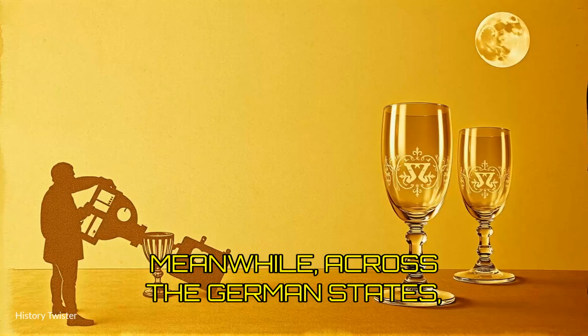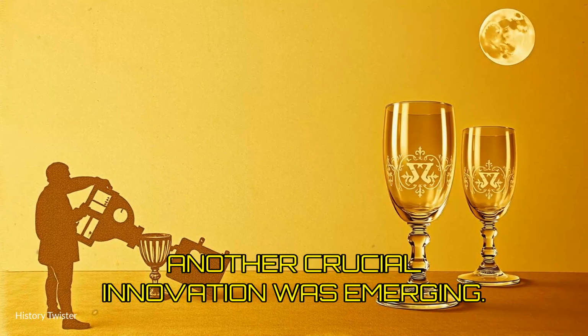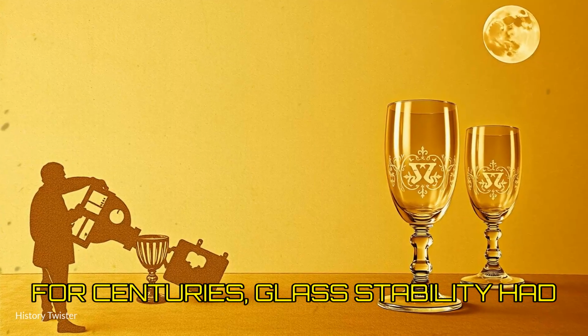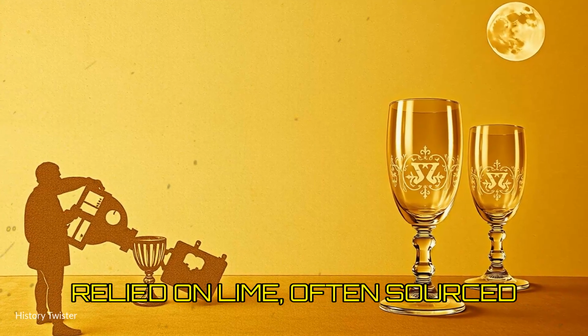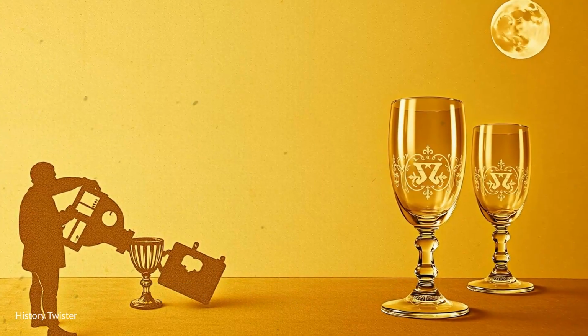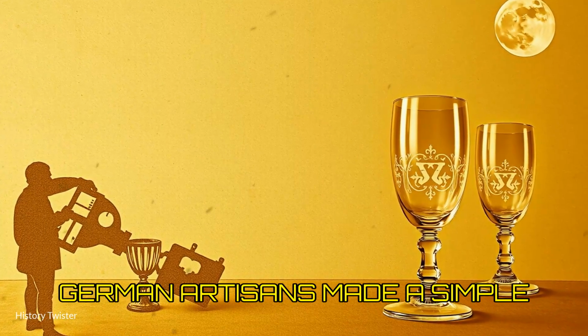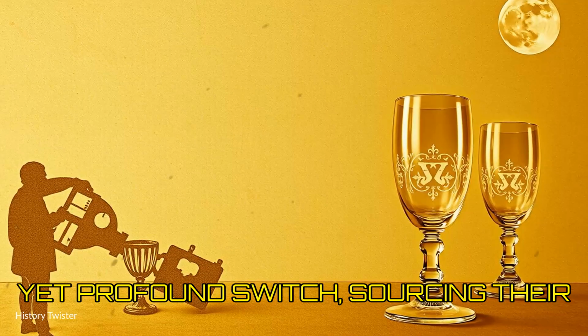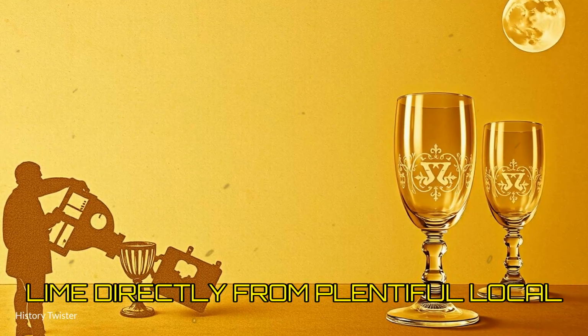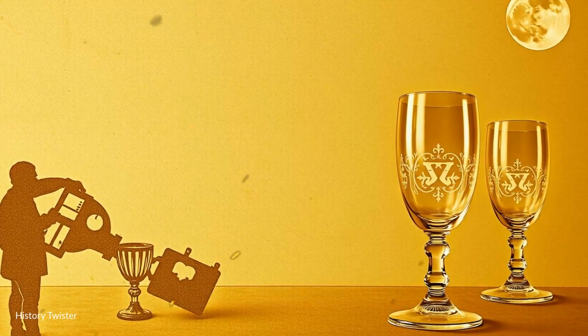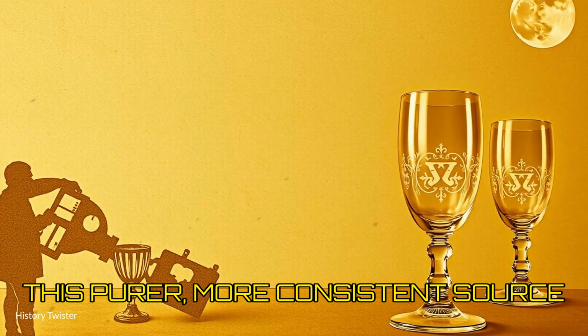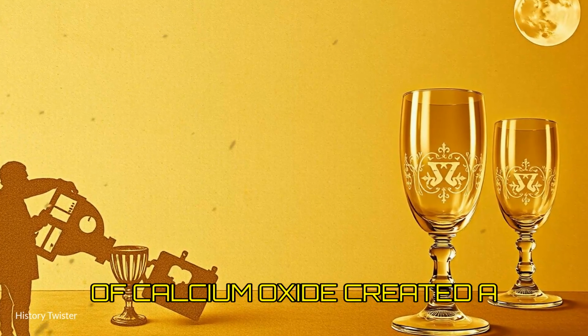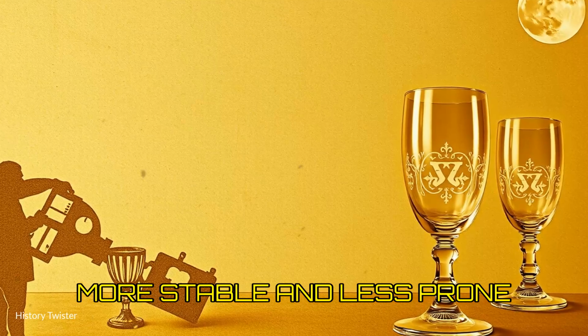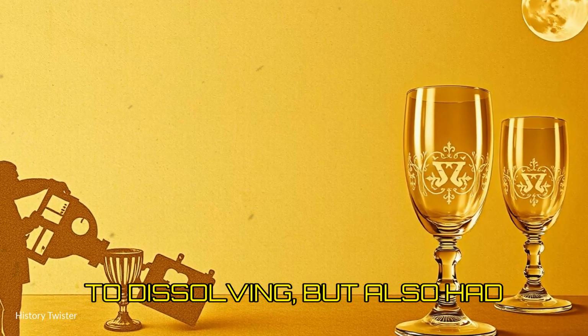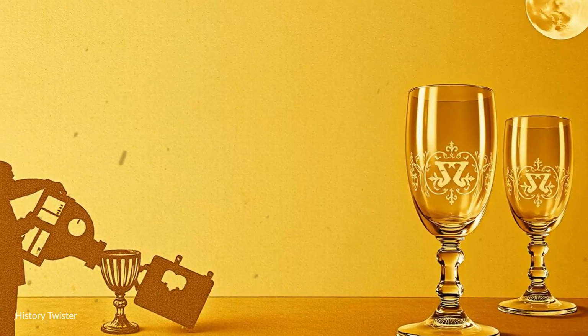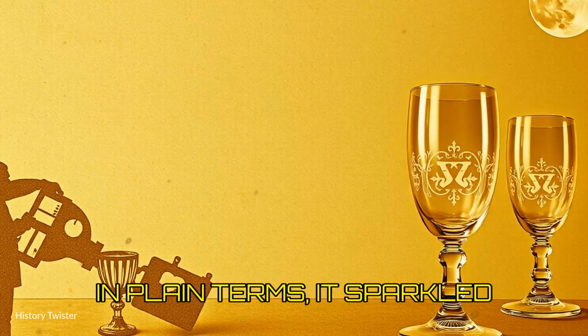Meanwhile, across the German states, another crucial innovation was emerging. For centuries, glass stability had relied on lime, often sourced from burned bones. German artisans made a simple yet profound switch, sourcing their lime directly from plentiful local deposits of limestone. This purer, more consistent source of calcium oxide created a glass that was not only more stable and less prone to dissolving, but also had a higher refractive index. In plain terms, it sparkled more.